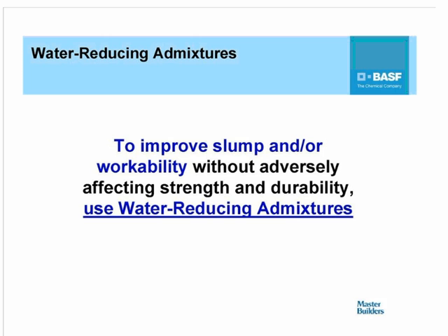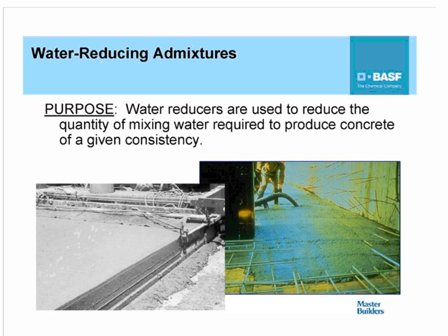And this can be done fairly easily through the use of water-reducing admixtures. By using admixtures, we can safely improve slump and/or workability without adversely affecting the strength and durability of the concrete that's in place. So let's start off and take a look at what these materials are. Well, as the name implies, water-reducing admixtures are used for the sole purpose of reducing the quantity of mixing water required to produce concrete of a given consistency. That's one of the primary reasons why these admixtures are used in concrete.